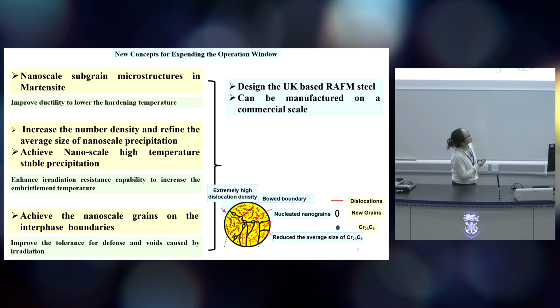Importantly, I will also achieve nanoscale grains on the interface grain boundaries. As we know, the irradiation will induce voids and defects on the grain boundary, which lowers the strength and increases the embrittlement. So if we can produce nano grains on the dual phase grain boundary, on the interface grain boundary, we are trying to avoid the voids coalescing and interconnecting to failure.